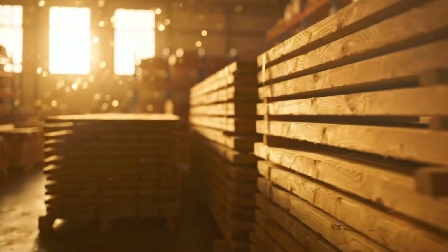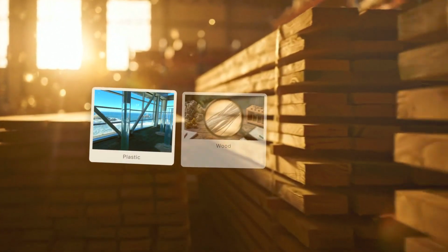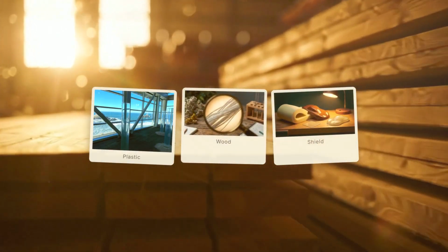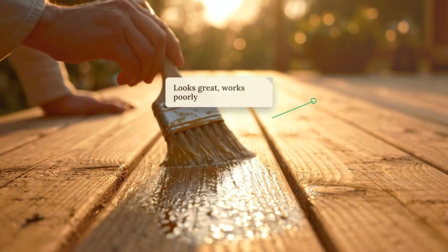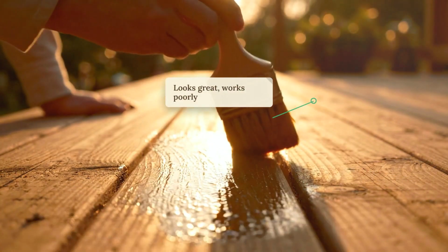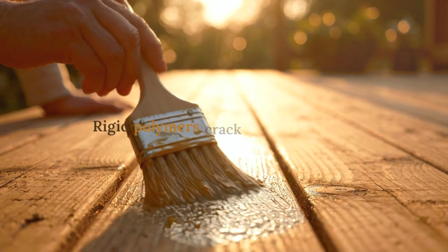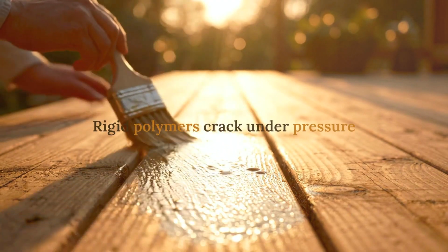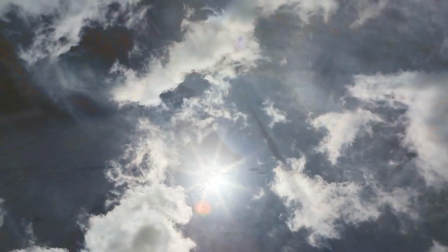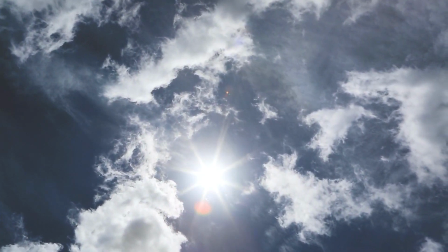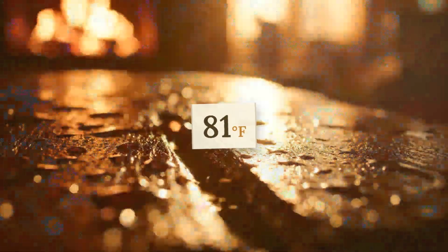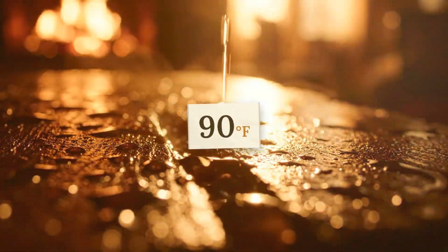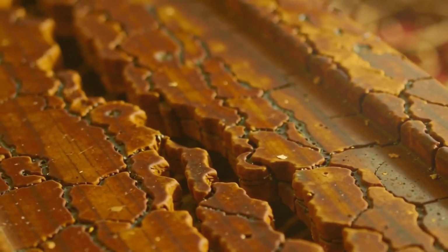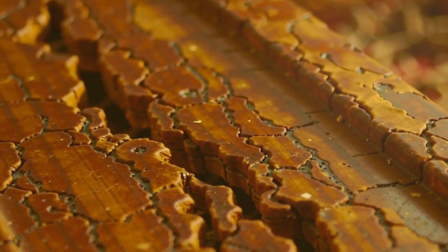Standard pressure-treated lumber contains bound water trapped within the cell cavities of the cellulose fibers. When you brush on a modern acrylic or polyurethane sealer, you are spreading a thin sheet of plastic over those pores. For 12 to 18 months, it looks fantastic. Water beads up on the surface, sliding off in neat little droplets just like the commercial promised. But acrylic resins are rigid polymers. As temperatures fluctuate between 40 degrees at night and 90 degrees under direct afternoon sunlight, the wood expands and contracts at 3 times the rate of the plastic shell glued to its surface.